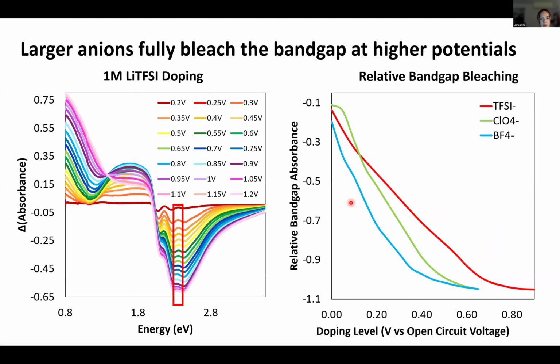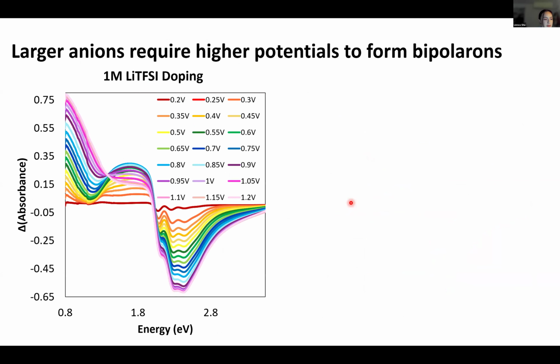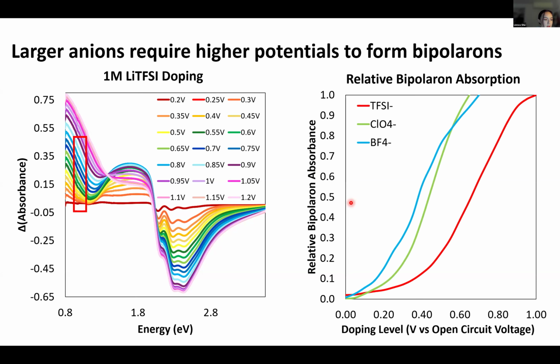And then we can also look at the bipolaron absorbance, which is this energy right here. And again, we can see that the smaller anions are creating bipolarons at lower potentials than our larger anion, which is in red, which is TFSI. So we hypothesize that this is due to the ability of TFSI to hold polarons at a greater distance from each other, thereby preventing them from coupling to form bipolarons.